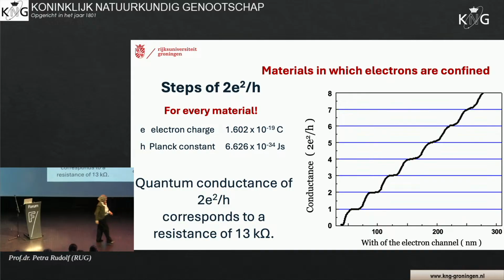This is not what happens when you have things at this quantum level, where the electron is very constricted. You see that you get these steps. And this is always the same number. It does not matter what this conducting layer is made of. Again, something completely different from normal material, where steel conducts much worse than copper, and so you don't get the same conductance for different materials. But here you do. So this is a very clear demonstration that at the quantum level, the materials really behave very differently.